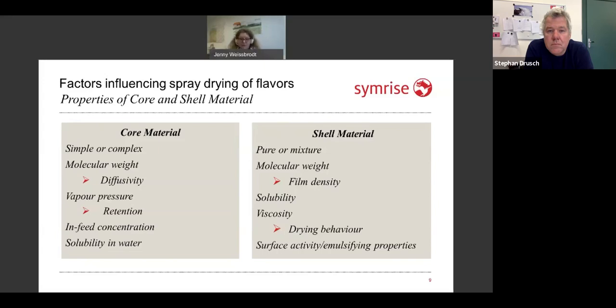Then the shell material. Is it a simple component, or do you use a mixture? Of course, if you need, for example, some surface activity or emulsifying properties, you might use a little bit of a more expensive emulsifier and then add some bulk material just to make the drying process itself more economic. What about the molecular weight of your shell material? Because this will determine the film density of the drying droplet directly at the surface, and this determines how much of your volatiles, for example, will be lost during the evaporation of water. Then the solubility, of course.